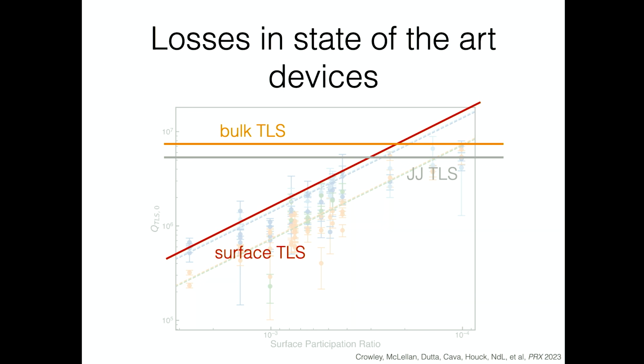like this. So we have some surface two-level system loss, some bulk two-level system loss, and we believe that these surface losses could be related to the surface oxide. They could also be related to the sapphire-air interface because that's the remaining other surface that we haven't really tackled. And then this bulk loss, which again is two-level system loss, has to come from defects inside the sapphire. So now there's a whole project of trying to understand what's going on in the sapphire.